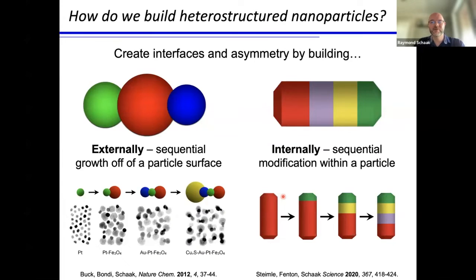I'll just mention two that my group focuses on. One is seeded growth. And again, there are many, many groups worldwide that do exceptional work on seeded growth. What we've been trying to do is push the boundaries of how many sequential seeded growth reactions we can achieve to start building up these heterostructured nanoparticles with the largest possible number of materials, controlled interfaces, et cetera. And we think of that as growing these interfaces externally off of a starting seed particle's surface.